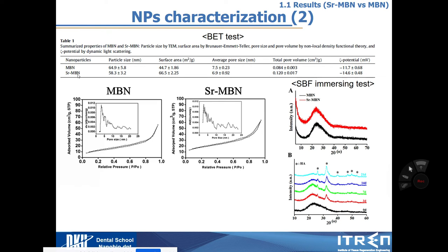And then I check their bioactivity in an acellular way, which means without any cells, I just incubate this nanoparticle with simulated body fluid, which is the same as our body fluid. From this, we can observe that hydroxyapatite is precipitated on both strontium MBN and MBN, which is called the bioactive property. When we say bioactive property, it means that when you immerse your bioactive nanomaterial, it should precipitate this kind of hydroxyapatite on your surface.